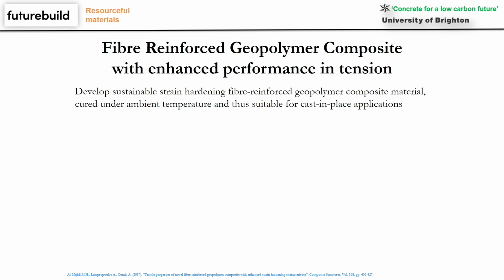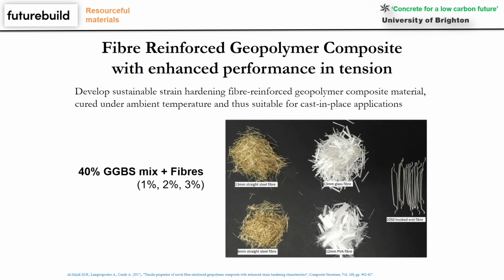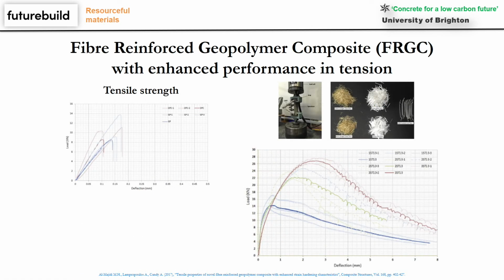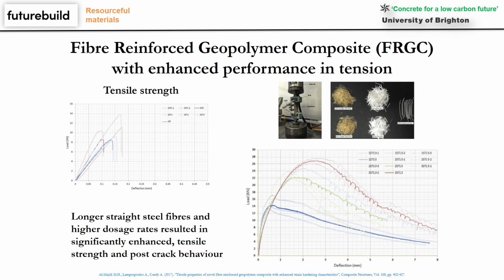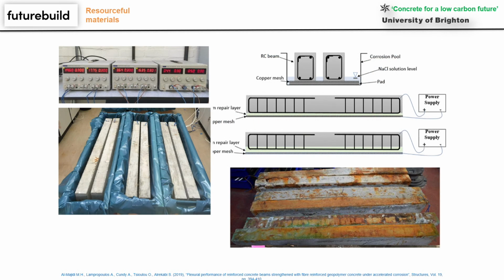Then we moved on to the actual application of this material for the strengthening and repair of existing structures. So we used the mix design that we developed in the previous study. We added appropriate types of fibers, steel fibers, polypropylene fibers, and we actually used these materials, which now have very high performance, good energy absorption, good tensile characteristics for the strengthening of existing elements. So we had our reinforced concrete beams, and we cast additional layers using this geopolymer high-performance concrete.